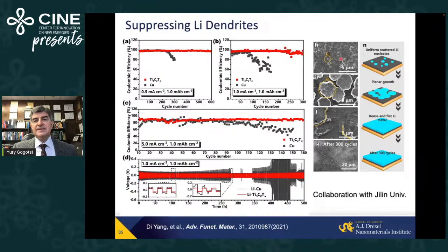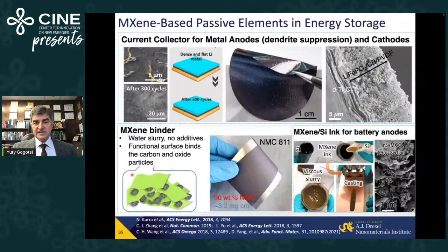For example, suppressing dendrite growth, enabling lithium, but also sodium, potassium, zinc metal batteries. Lithium grows in a planar way on MXene, unlike copper. And again, unlike copper, these black traces here, which lead to dendrite instability, one can get stable deposition and dissolution of lithium over 100 cycles.